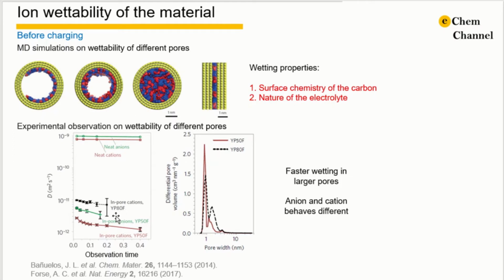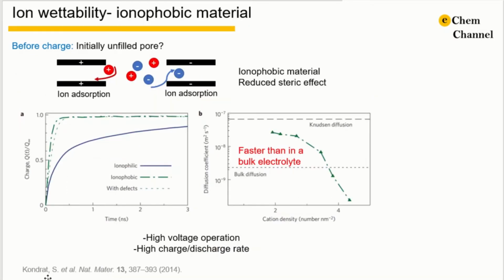YP80 has a relatively larger pore size compared to YP50, so the diffusion coefficient of the cation is much faster in YP80 than YP50. It can also be observed that the anion diffuses faster than cations in YP50. All these simulative and experimental results show very clearly that the pore of the material is already filled with electrolyte before charging.